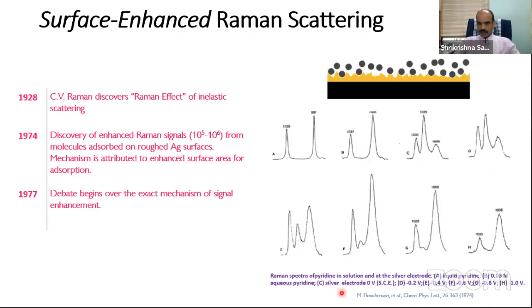It was a 0.05 molar aqueous pyridine solution. He could observe the pyridine Raman spectrum, and this was a very extraordinary result. A very small amount of pyridine could be measured on the silver electrode, and then people started to discuss, and the debate started. Is it mainly because of the roughness of the surface of the silver, or is it because of the silver itself?